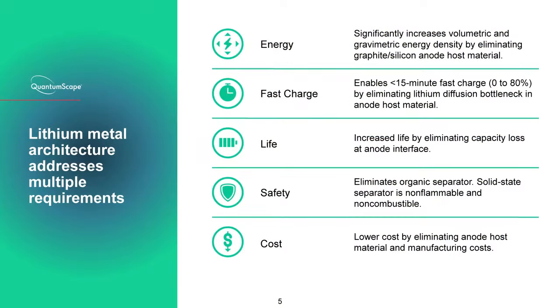So first of all, the fact that we have an organic electrolyte consisting of a polymer and a liquid combined into an organic gel-like material has been in our public disclosure since the S-4 was filed way back last year. So that's been fully transparent. Here's the important point. All the benefits that we're talking about, from energy density to fast charge to safety to cycle life and cost, they really stem from the solid state separator, right? That's the material that is both an ionic conductor and an electrical isolator. So it isolates the anode from the cathode, which prevents dendrites. That material is what allows you to switch to a lithium metal anode, right? And the lithium metal anode delivers all these benefits to you.